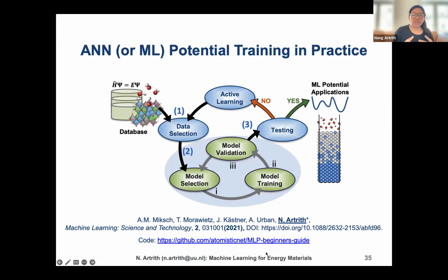So basically, we generate a database and then we select and analyze the database to see if it's really reliable and also accurate and also good enough for our applications. But most of the time, we don't have the complete reference data directly. We always have initial data. And then we go to the second loop, with model selection or model training, and then we can start to validate, and then we can test the model. If it is not good enough for the application that we want to use, then we also include another feature or features by using active learning to help, and then increase the database that we have. And then we do these iterative refinements until we get the right machine learning model that we want to use for our own applications.